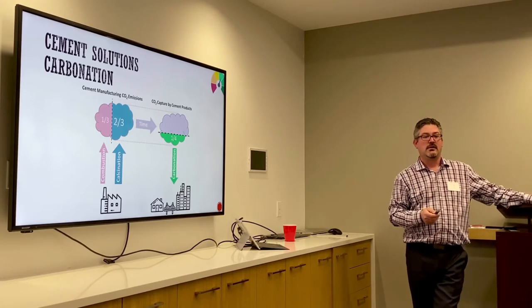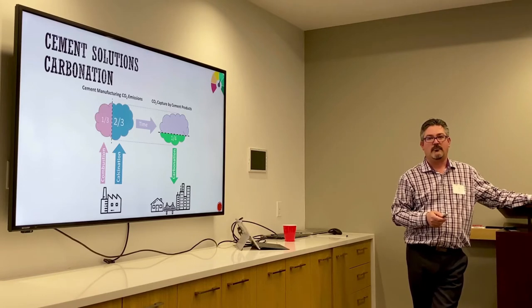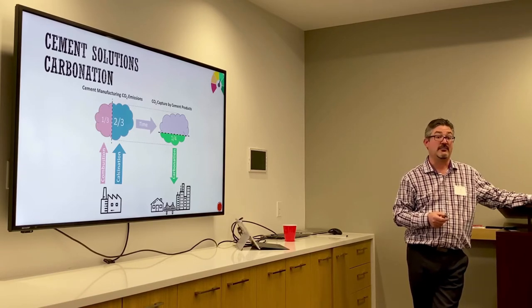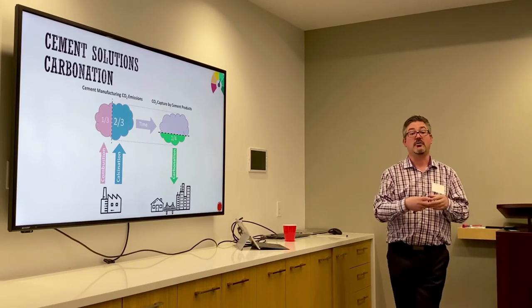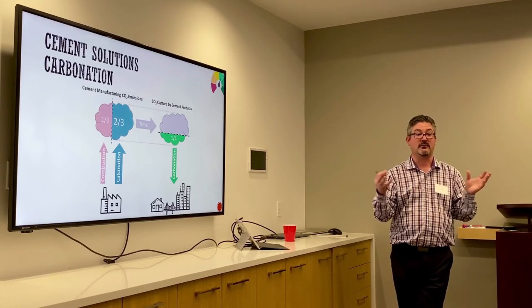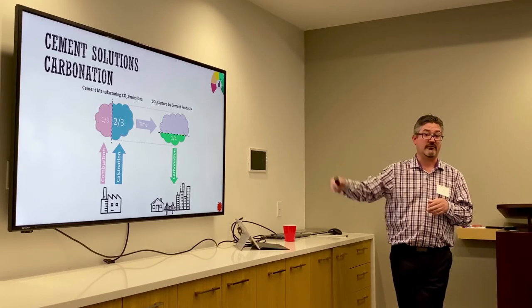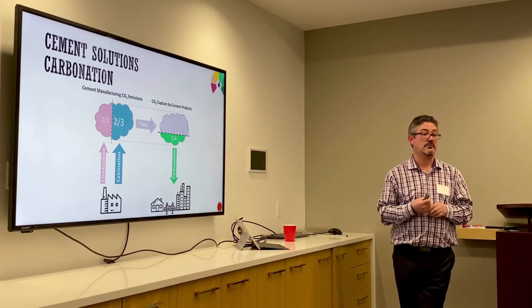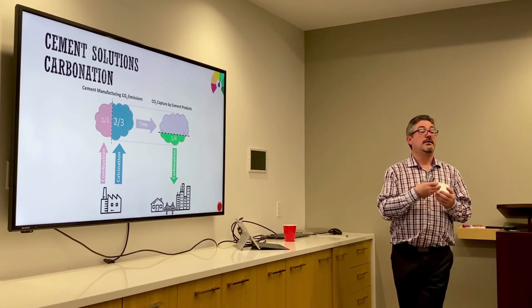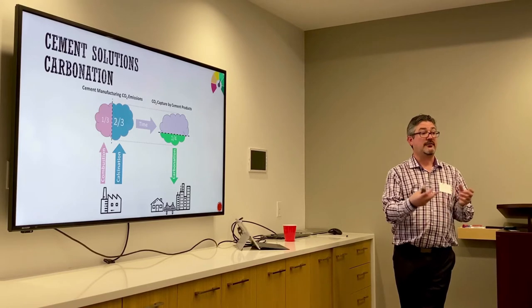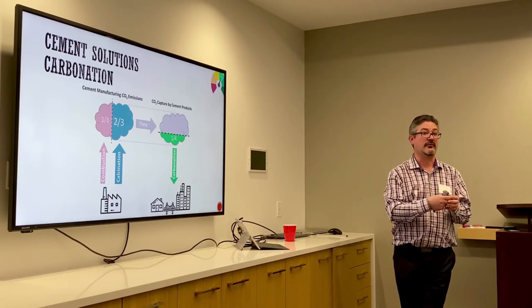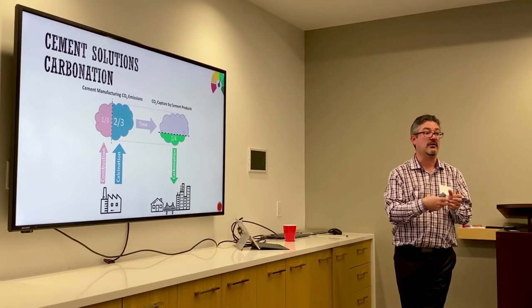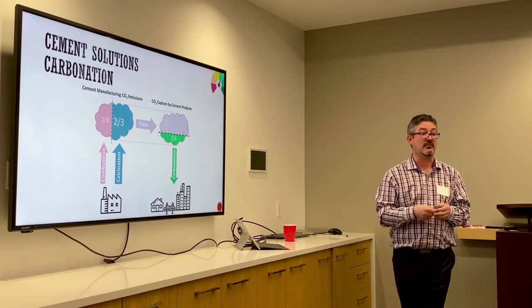Sorry, but the time scale, is it 100 years, more than 100 years, to actually sequester that amount? It really does depend, particularly on surface area. If you crush concrete, for example, that gets absorbed very quickly. If you're looking at large buildings with a small surface area, that could be in excess of 100 years. Wouldn't most of that happen when it is demolished? When it's demolished, you're increasing the surface area of the concrete, and that allows more surface area to absorb CO2, and yes, that does have a significant jump in the carbonation at that point.